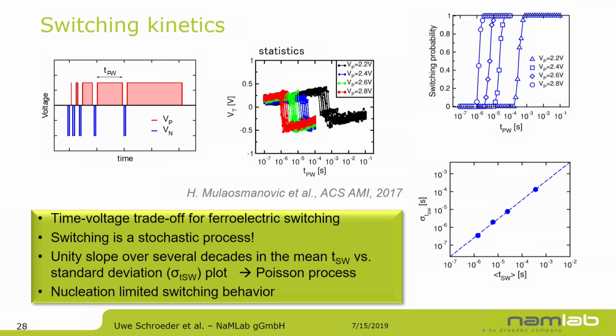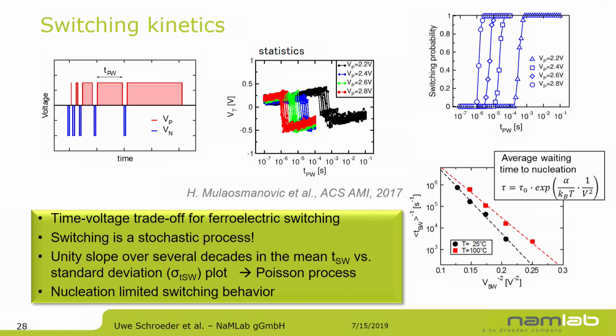And now you can do a little bit of statistics on it. If, for example, you look at one voltage and you do this 10 times, you can see that every time it behaves a little bit differently. You can get the switching probability, and overall you see that switching is a stochastic process, and you have a Poisson distribution for all these switching events. And again, we can look at the different voltages here, and you can see we have nucleation limited switching behavior, so 1 over v square behavior for the switching event. So independent of whether we look with the PFM at the capacitor structure or the transistor structure, as expected we get this nucleation limited switching behavior.